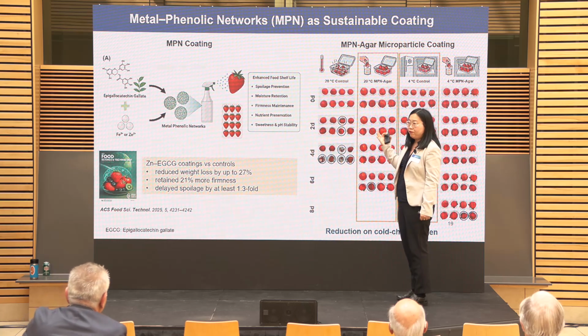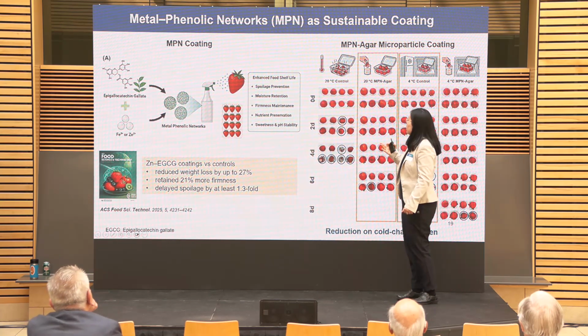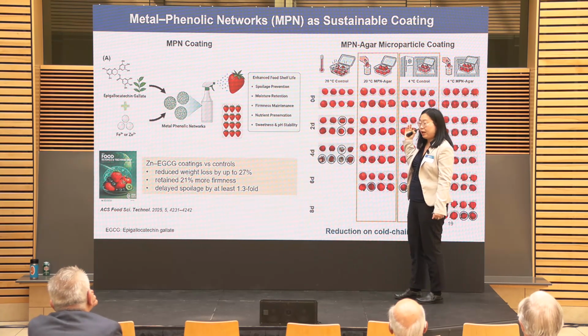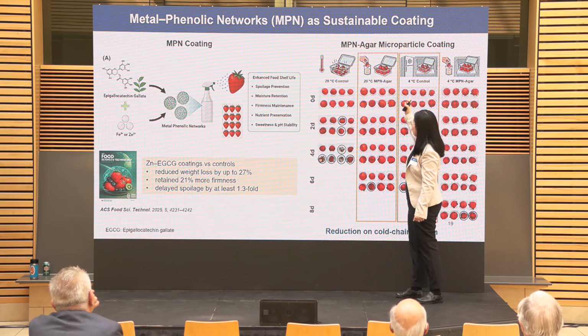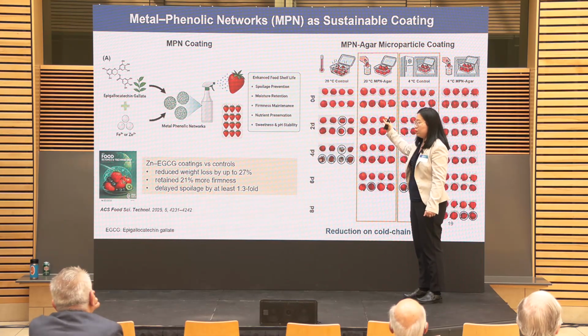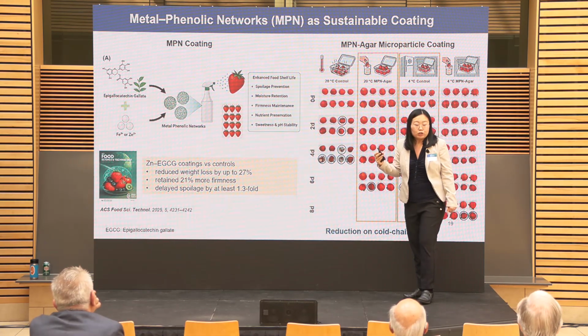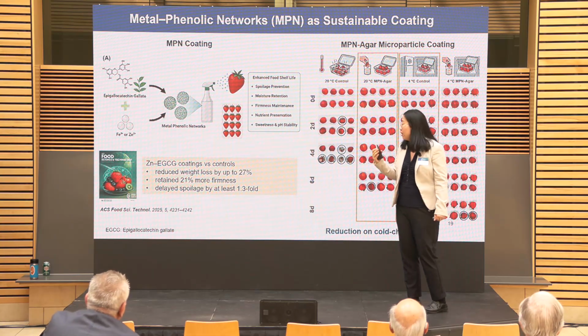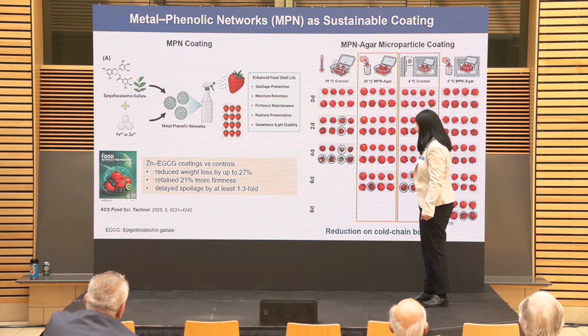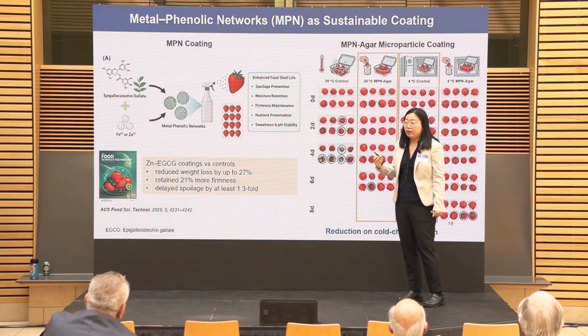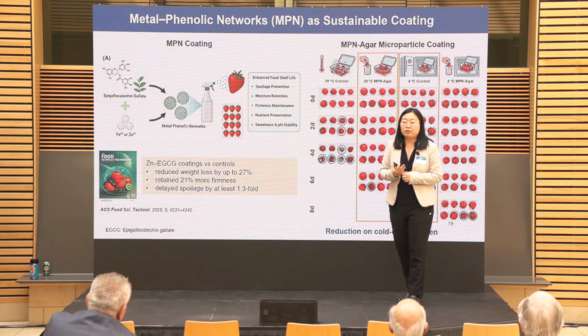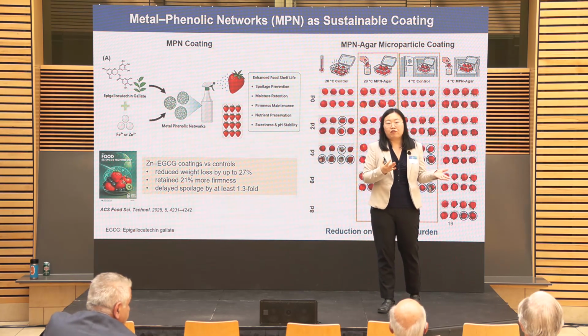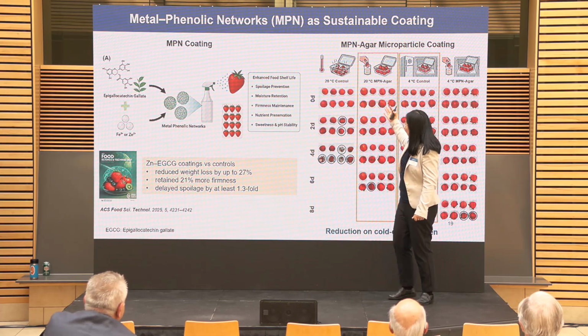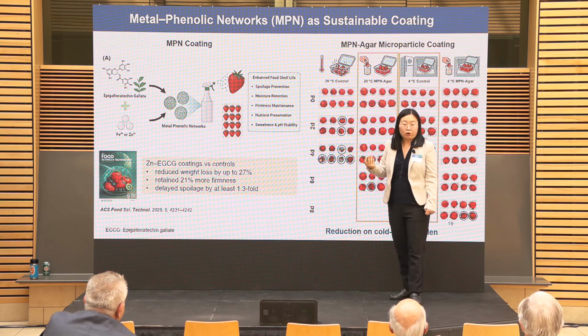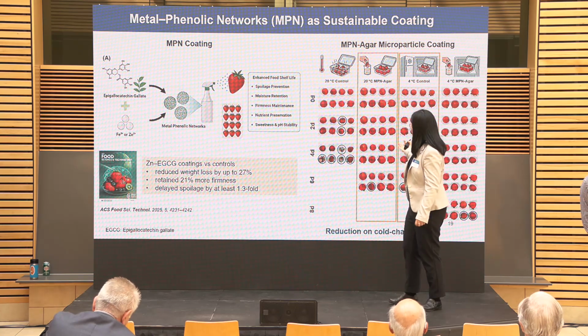And we compare the coating performance with the fridge conditions, so at room temperature as well as at fridge temperature. Very exciting is when we compare the coating at room temperature with the fridge without coating, we found that our coating performance is actually much better. This is super impactful because this can reduce the cold chain burden. This is very important for transportation when we ship or transport fresh produce internationally. So this can help us to reduce the cold chain storage as well as for further evaluations.